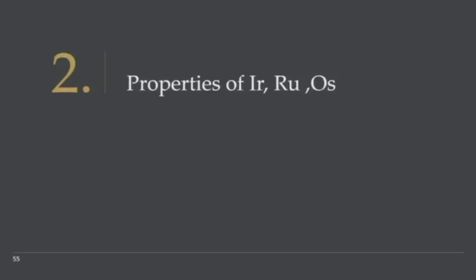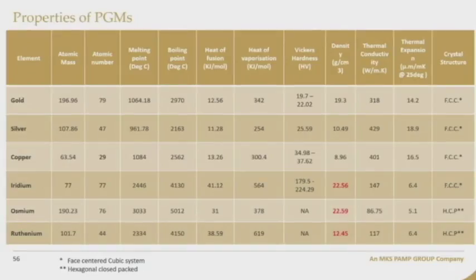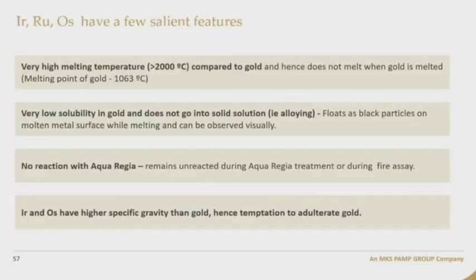Before I go into the results, and Pankaj will explain the machines used, I want to state the properties of the PGMs. What I would like to point out is the density of iridium and osmium is much higher than that of gold, and that of ruthenium is much lower, almost 12 as compared to the density of gold, which is 19. And this formed a basis of our analysis. A few of the other salient features are that all these PGMs have a higher melting point of 2000 degrees centigrade, so they do not melt when gold is melted.